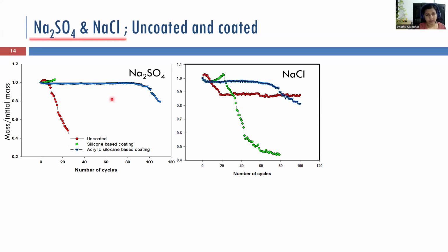This is the case of sodium sulfate, which we just discussed before, why this was happening - crystallization pressure. In case of sodium chloride, the uncoated samples, the red one, are not damaging even at 100 cycles, same with acrylic siloxane based coating. But when we are having a silicone coating, we could see that damage is initiating early.